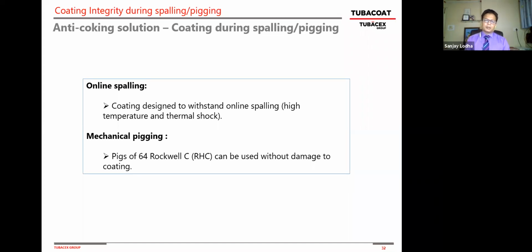Second part is mechanical pigging. Of course, our regular pigs, which are 82 or 84 Rockwell C, are a bit too hard for something like this coating. So we have worked with the coking company, and we have come up with the pig studs. Those are a little bit softer, 64 Rockwell C or 800 Vickers number, and they can do the mechanical pigging without any damage to the coating surface. And they can be available to any customer anywhere in the world. So we just modified that.